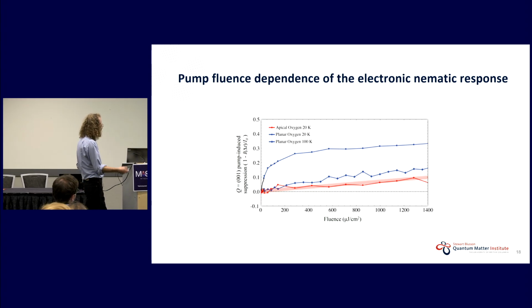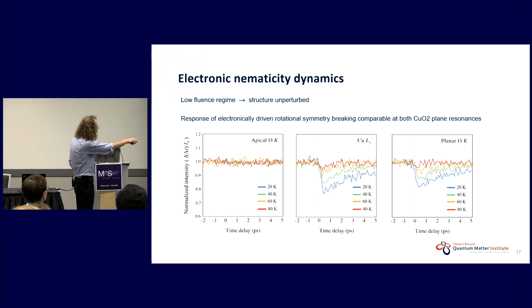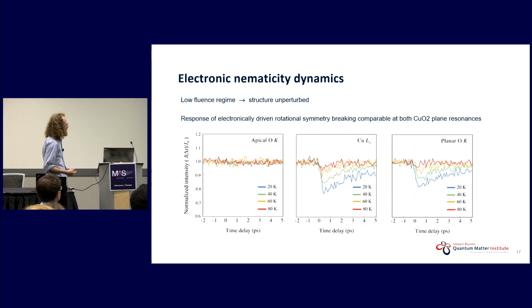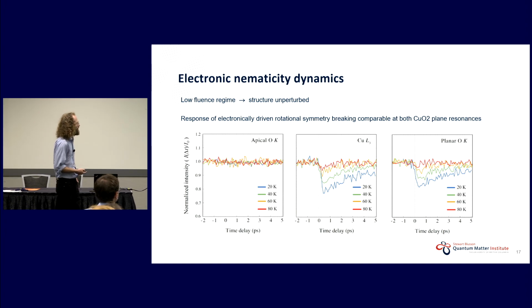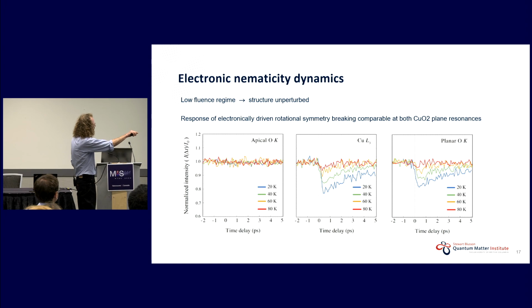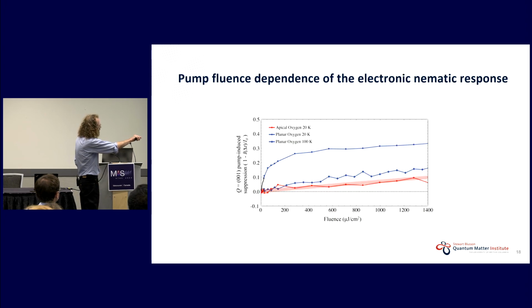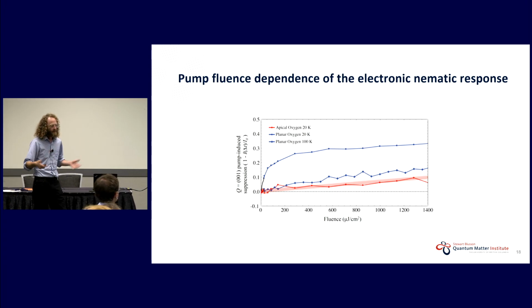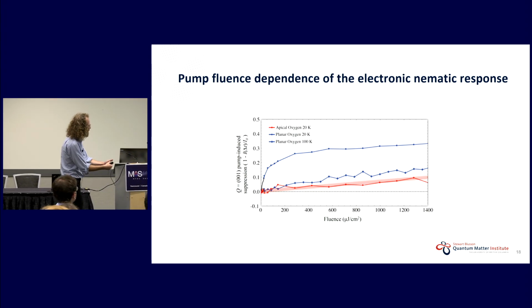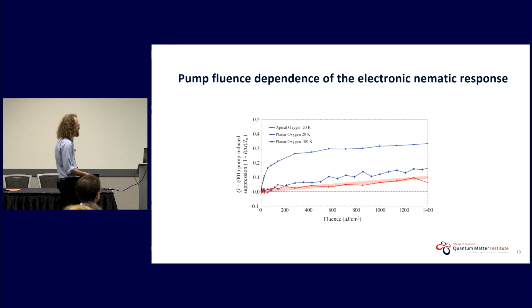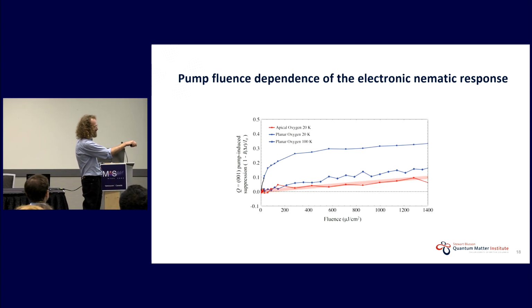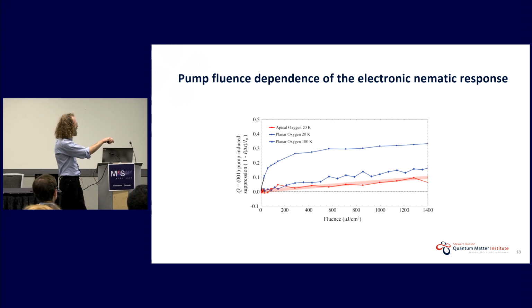Well, okay, so then we try to study the fluence dependence of this thing. So we sit here at the time delay of maximum suppression. And since we have a very strong signal, we're able to collect this data in a very modest amount of time. We now do a fluence scan here, and we see if you go at the apical oxygen associated with the structure, you see a very weak linear response in the whole fluence regime that we have. This is telling us, yeah, we're in a linear response regime. The lattice is just getting more and more perturbed, but only slightly as we increase the fluence. If we go to the planar oxygen resonance at high temperatures above the CDW phase, we have the same sort of response. But if you cool down into the CDW phase, this upper curve here, then you see there's this fast saturating response at low fluences, and then something that looks more like the structure at high fluences, okay?